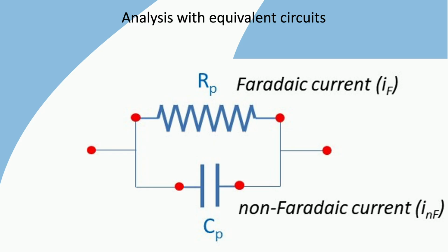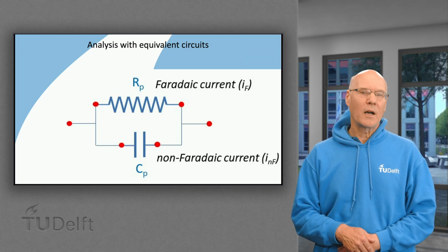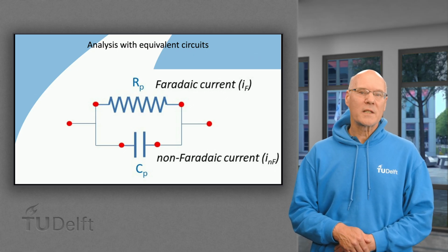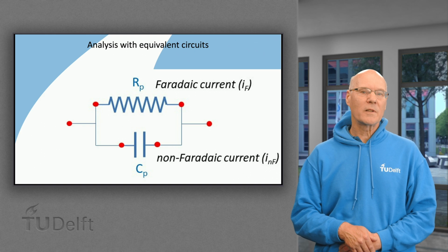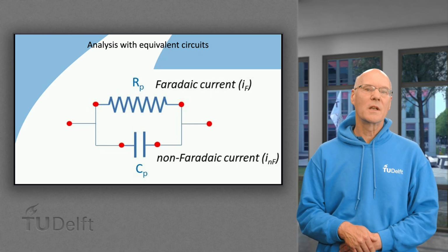To characterize the electrochemical process, the system is analyzed by impedance spectroscopy using a small amplitude AC signal by varying the AC frequency, and therefore it is called impedance spectroscopy or electrochemical impedance spectroscopy, EIS. This will thus be analyzed by the measured complex plane, referring to the impedance data or admittance data. This, after a short introduction to the complex impedance and admittance of a system, several equivalent circuits and the relation of the circuit's components to the physical processes are shown.